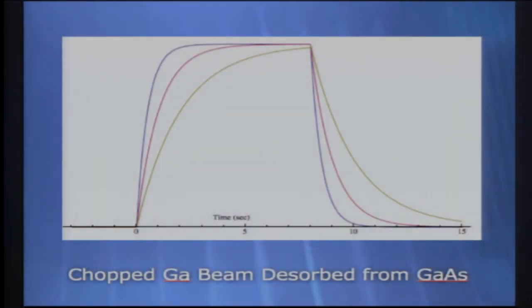That's just a mathematical depiction of what it looks like at three different temperatures. But it's a first-order differential equation. The solution is straightforward. You get an exponential, one minus exponential rise and an exponential tail on the thing. And that's exactly what we found with gallium on gallium arsenide. Furthermore, the enthalpy of vaporization, which you get from the temperature dependence of these curves, agreed exactly with what we'd already measured in the mass spectrometer experiments. So this was behaving perfectly normally.